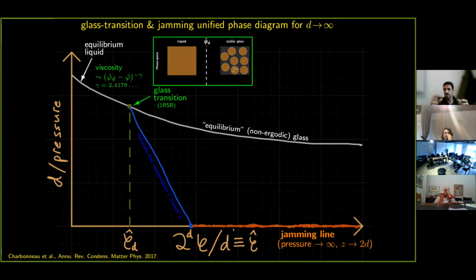system is assumed to be constant and the particles are rattling in their cages. Once you compress it, the pressure explodes, goes to infinity, and then you have a jamming line that extends from that random loose packing and onwards. At this line, no matter how you arrive, if you start from the equilibrium glass transition or deeper in the equilibrium non-ergodic glass, you would always arrive at the jamming line when the number of contacts approaches exactly 2 times the spatial dimension.